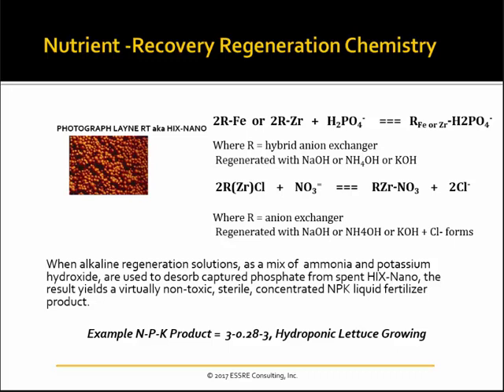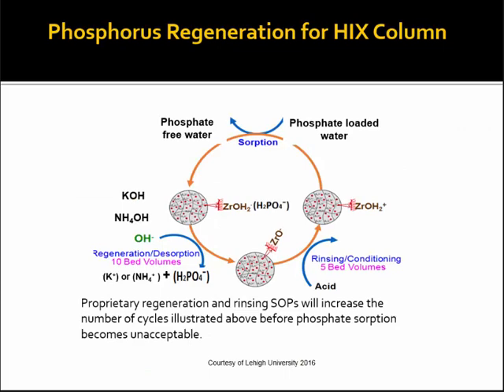So there's a new formulation using zirconium oxide nano on a chloride form resin, and that's why I did iron or zirconium in the ligand reaction. But I could do straight ion exchange reaction in the chloride form, regenerate with like KCl and release nitrate. So here's an illustration of the chemistry. You have phosphate loaded water, sorption, phosphate free water as the effluent.